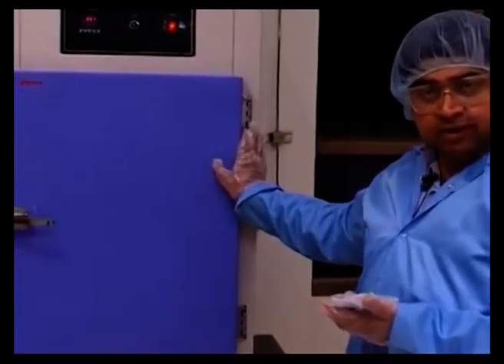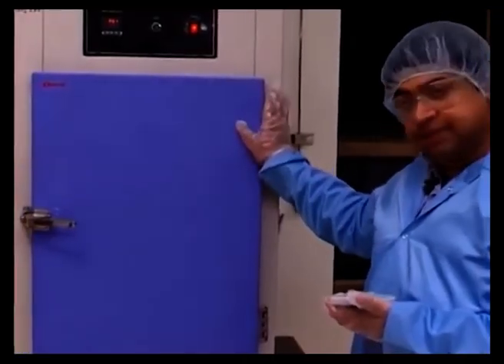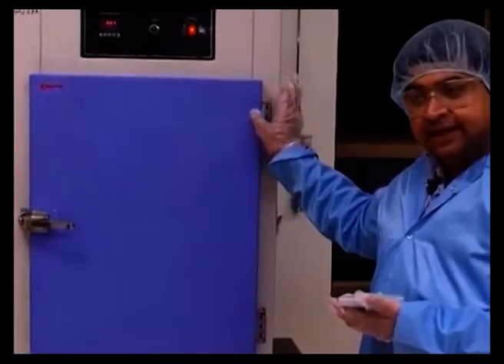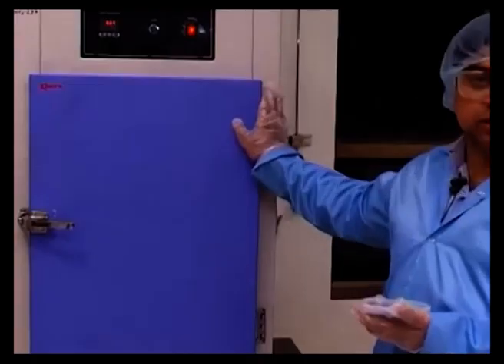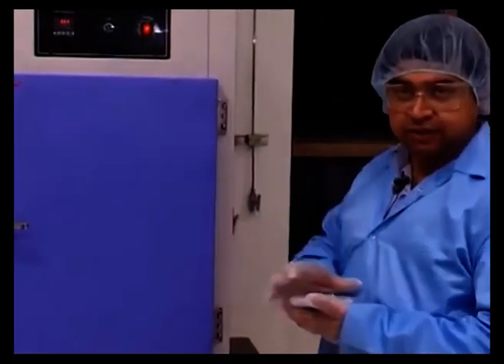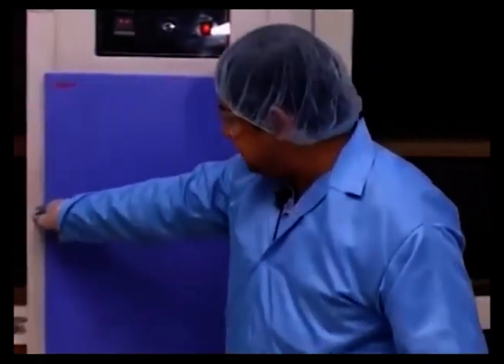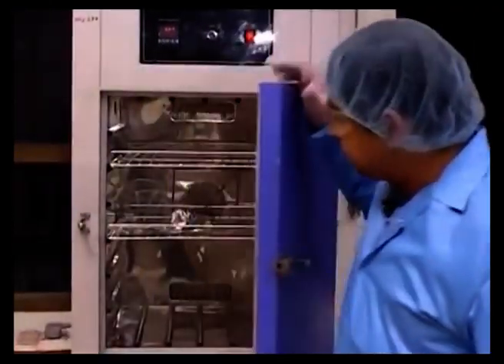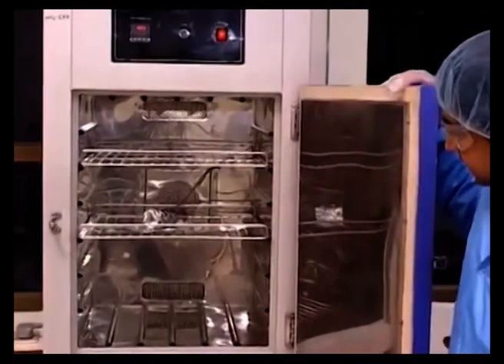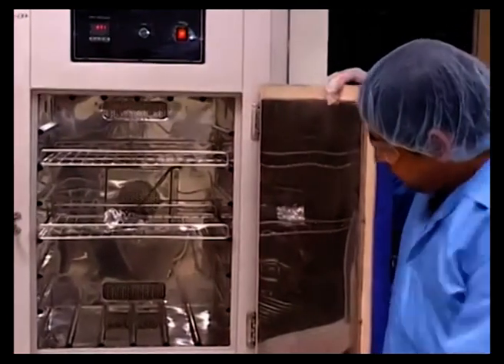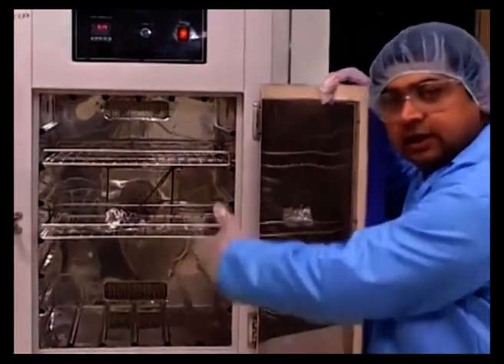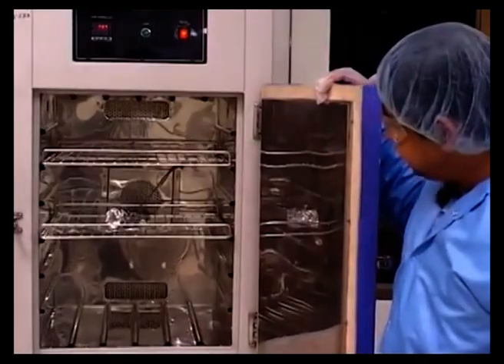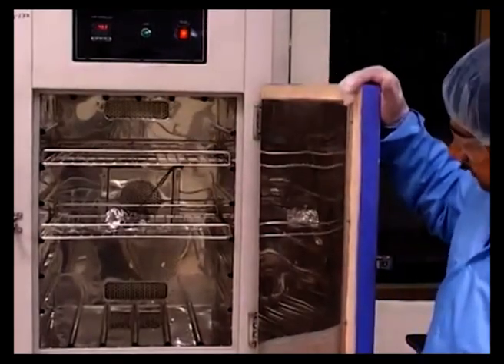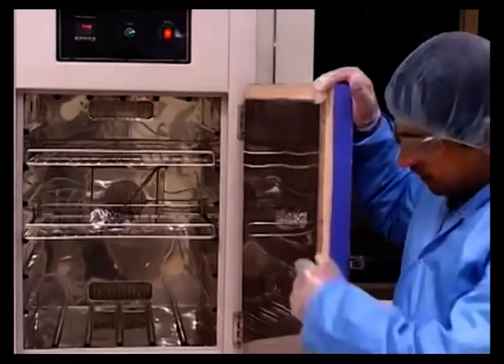This right here is that oven. So what I am going to do is to illustrate a little bit about this oven, and then basically use this oven to heat dry the wafer surface. So basically, if you look at this oven, really it is a shelved oven. As you can see, there is a fan which actually does forced convection along this whole area, and essentially the wafers are kept at various levels. The thermocouple is somewhere at the bottom.